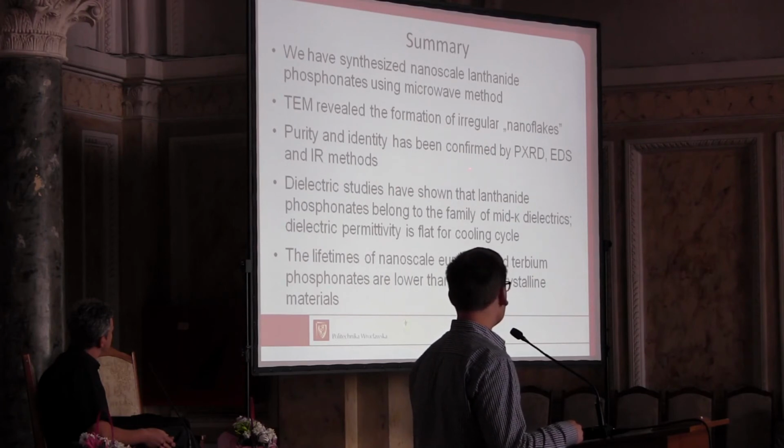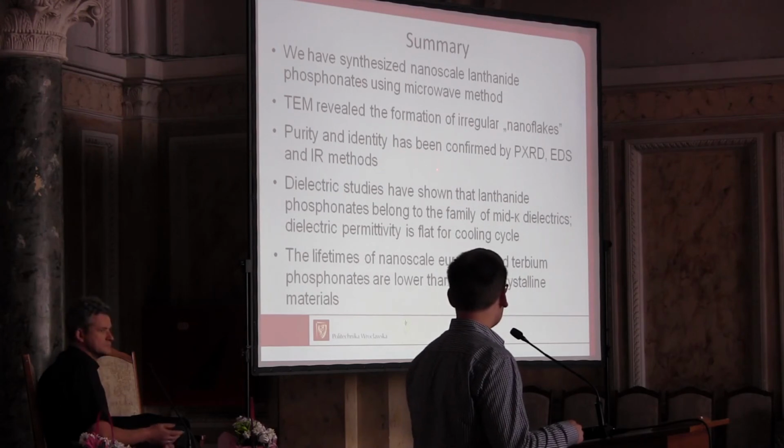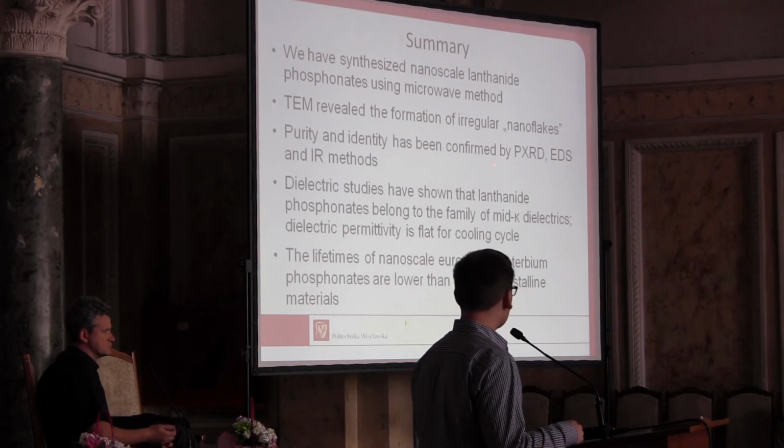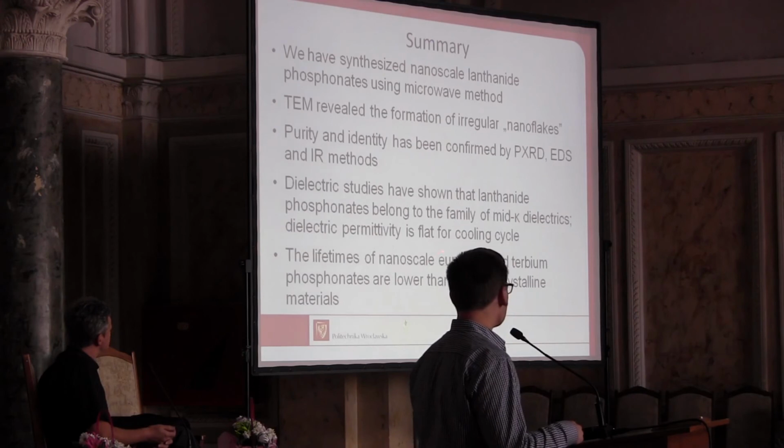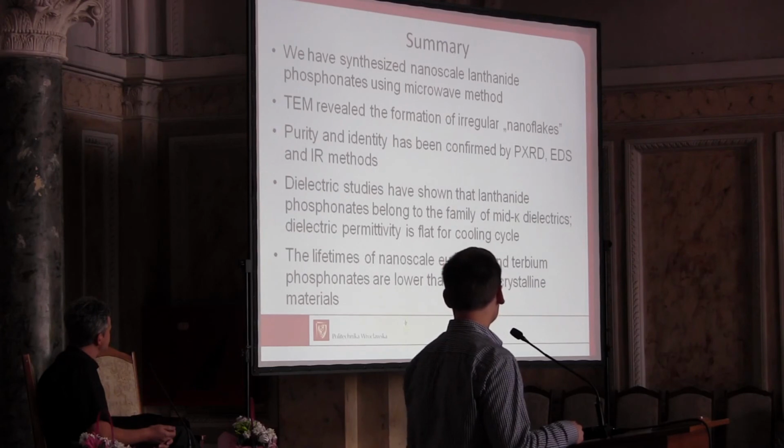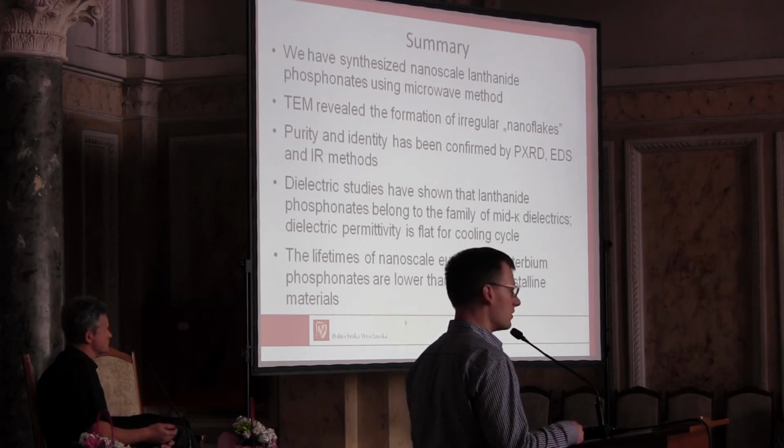Purity and identity have been established with powder diffraction and other methods. Dielectric studies showed that our materials are mid-K dielectrics, and the dielectric permittivity is flat during the cooling cycle, and the lifetimes of nanoscale europium and terbium phosphonates are lower than for microcrystalline analogs.